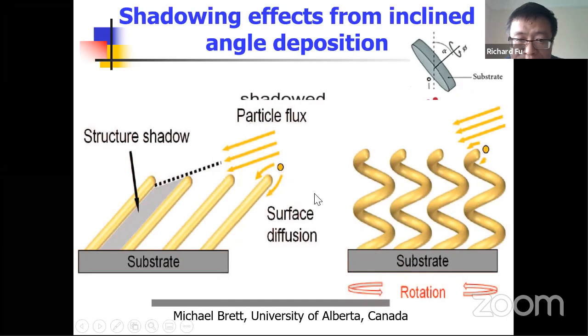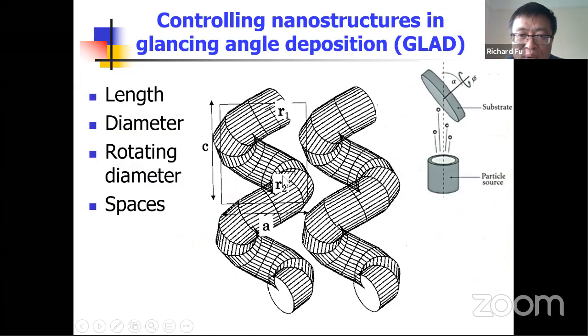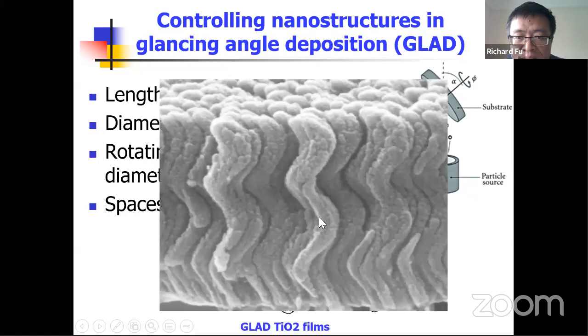If you deposit not only at an inclined angle but also while rotating, you will get a spiral pattern. This spiral pattern can be controlled precisely because you can control the angle, you can control the rotation speed, you can control the different functions. Then you realize different distances or diameters.